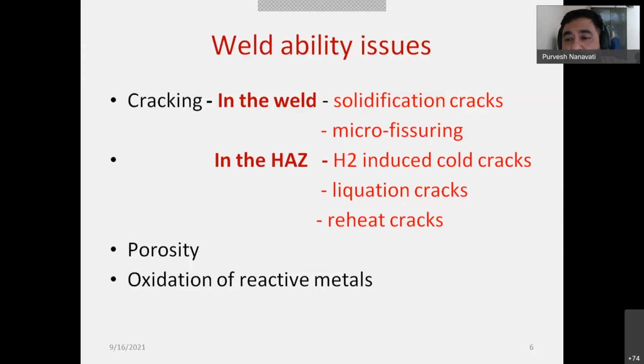Then in the heat affected zone, hydrogen induced cold crack. Sometimes during welding, when there is not sufficient shielding to the molten pool, either by flux or by shielding gases, the hydrogen from the atmosphere will react with the molten pool, and there is every chance that this atomic hydrogen gets diffused in it. So this molecular hydrogen, particularly from the air, gets dissociated into atomic hydrogen on coming in contact.